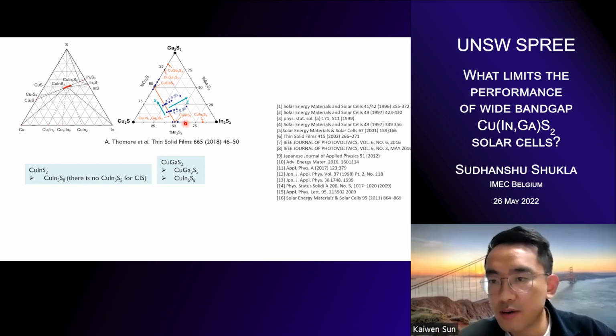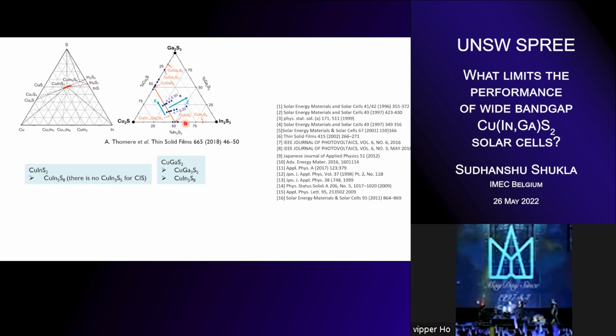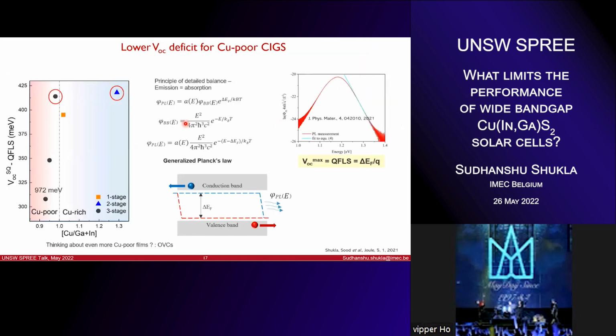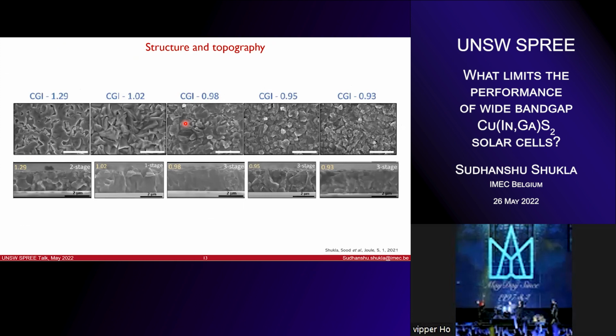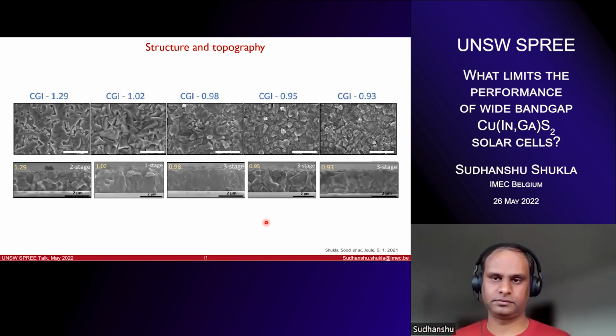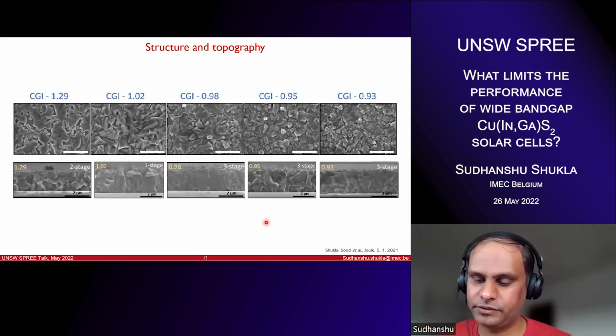Thank you. Any other question from the audience? Yes, okay. Yes, I have a question. From the SEM results, we can see that even though in Cu-poor condition your grain size is large and you have formed a quite flat surface, have you ever experienced, because indium is quite easy to accumulate during heat treatment or the sulfurization process, indium accumulation on the top surface that makes the morphology quite rough? And if so, how do you control it? Yeah, so thanks for asking this question.